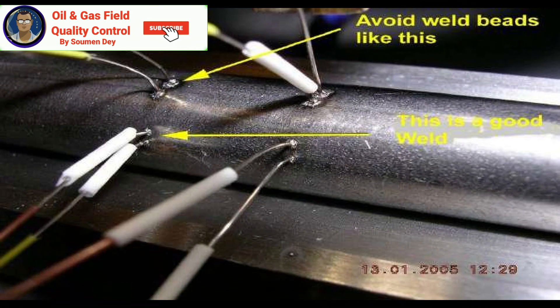The thermocouple shall be placed on the joint in firm contact with the pipe as near as possible to the weld area. Thermocouples should be directly tack welded to the joint or heating band, provided they have a tail of the same material. An approved filler wire electrode not larger than 2.5 mm in diameter is used for tack welding. To avoid incorrect temperature readings due to direct radiation, thermocouples shall be protected by ceramic fiber blanket or other suitable insulation. Heating resistance elements shall be laid over the thermocouples throughout the heating band and insulated with mineral wool or glass wool, with minimum insulation thickness of 50 mm. Wire mesh shall be wrapped around and tied to hold the insulation in position.